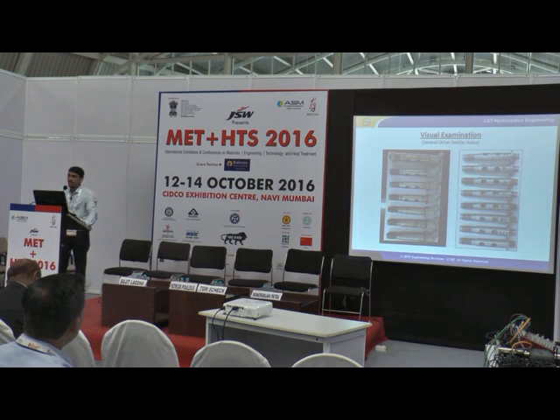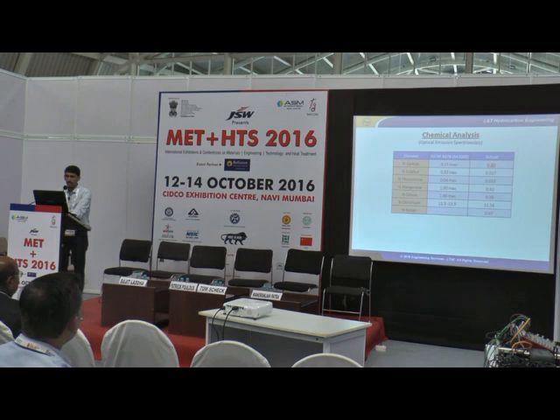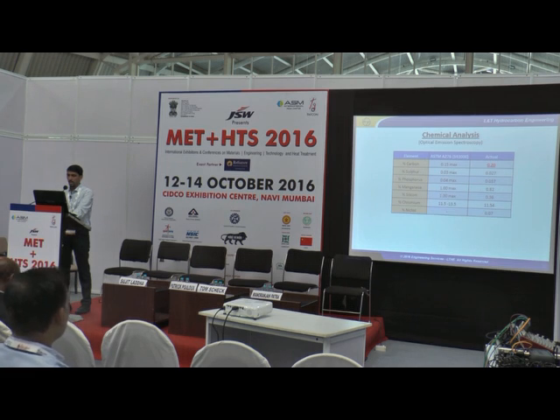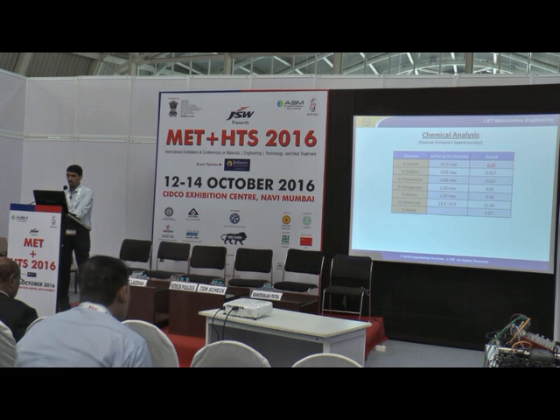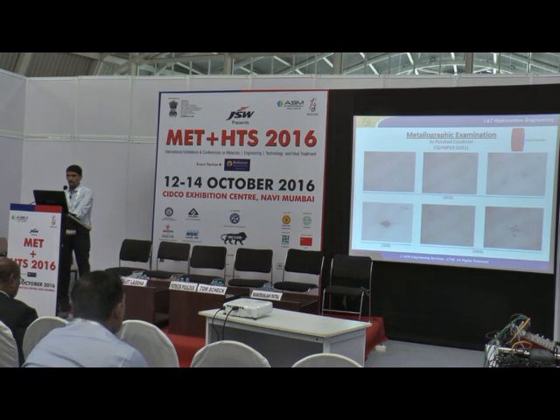In the next slide, you can see a similar axle at site conditions which was completely fine after test firing. No bending, no deformation, no fracture, nothing. But what has led to the fracture of this axle? We'll see soon. Chemical analysis of the component confirmed that it was meeting the specification of SS410 except the carbon content, which has exceeded the 0.15 max limit. A few more points on the 0.2% carbon content later. The metallographic examination in as-polished condition reveals a lot of inclusions and micro cracks.